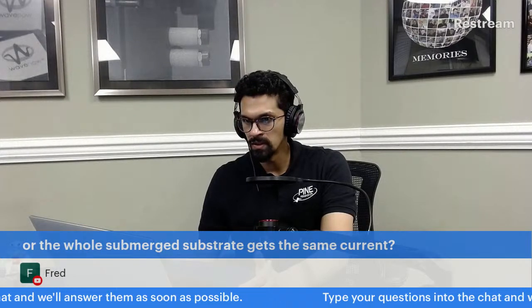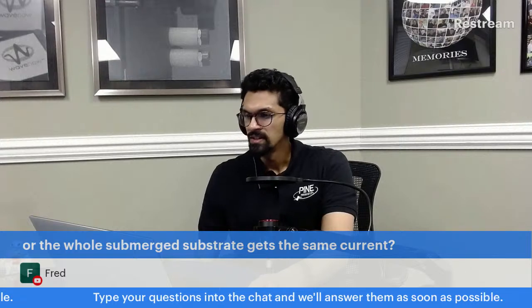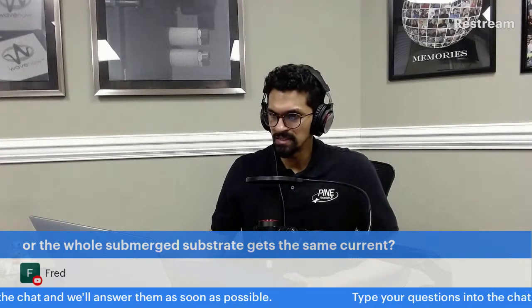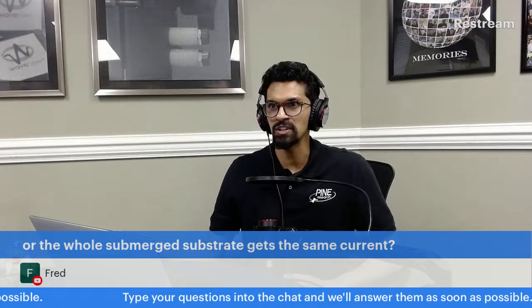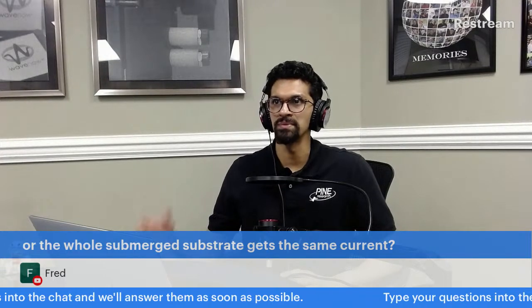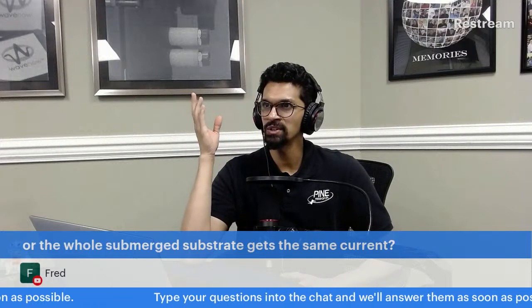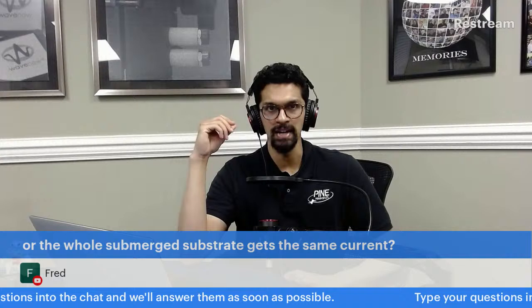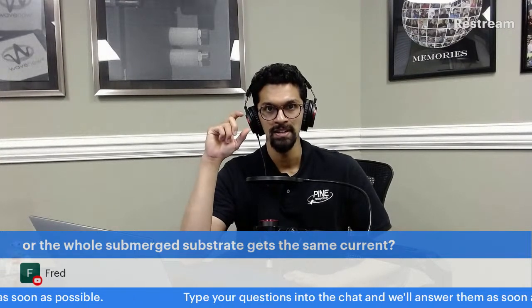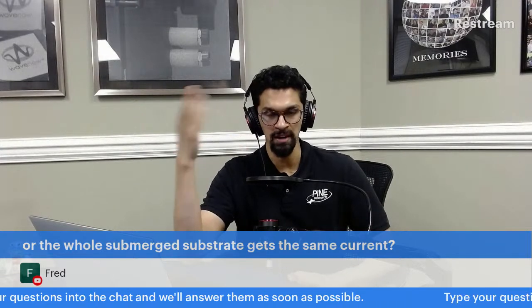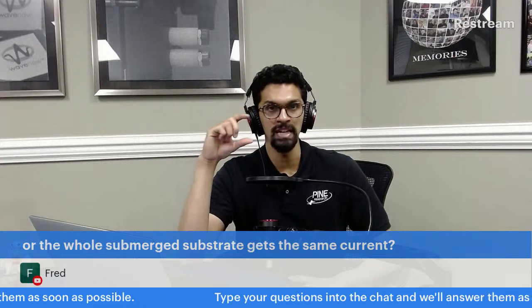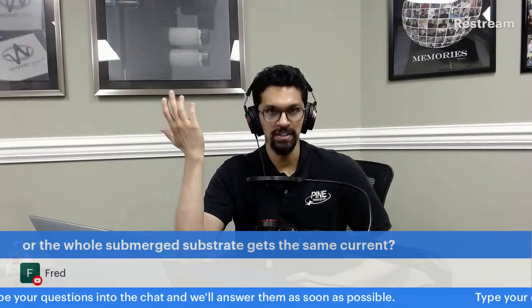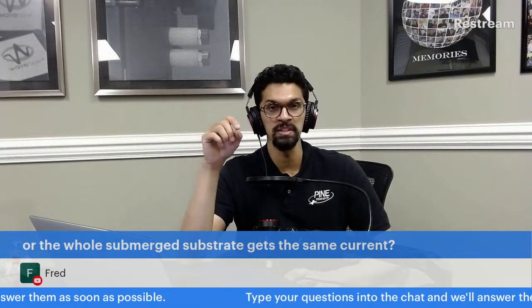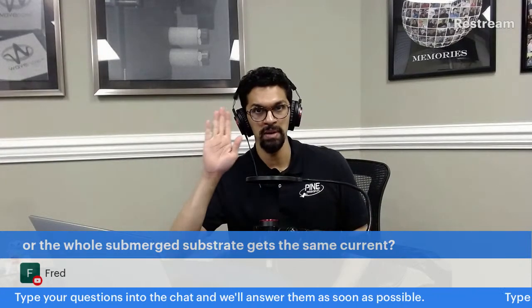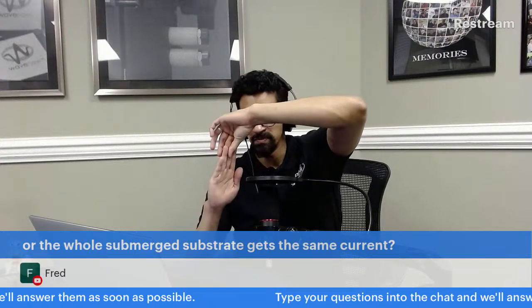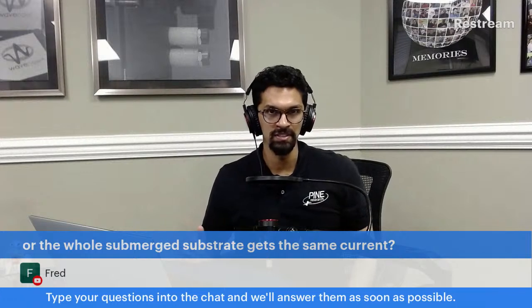You have kind of a separate thing: does the whole submerged substrate get the same current? Okay, I see. So ideally, I would say the current density. When you set your potentiostat in a galvanostatic mode and say, okay, apply minus 0.7 milliamps, it just makes it so that current is going to flow between the counter and working electrode such that 0.7 milliamps of current is measured at the working electrode surface. How that current is distributed may very well be based on the morphology. It's certainly based on what is submerged into solution. So if you have a plate with an alligator clip on it and you submerge it, there are some parts that might not be in solution. Well, they're not going to feel any of the current.